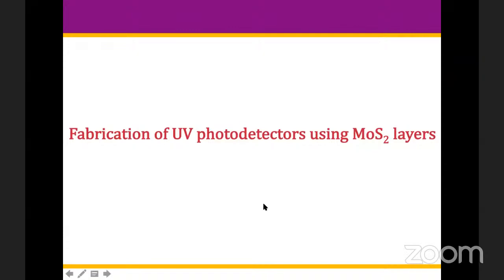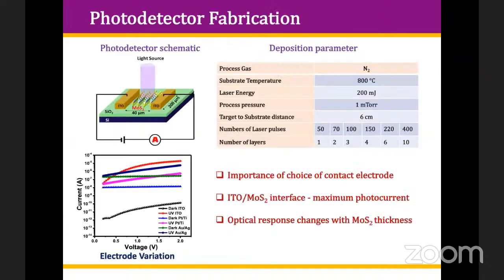Now, I will go on to the application part. Since MoS2 has been grown as monolayer, bilayer, trilayer, etc., we tried to make a photodetector. We put the bilayer, monolayer, and all different thicknesses of MoS2 here, and two electrodes of ITO are put, which is transparent and not going to obstruct the light. Then we applied some bias, around 2 volt, and studied the photo response characteristics of this.